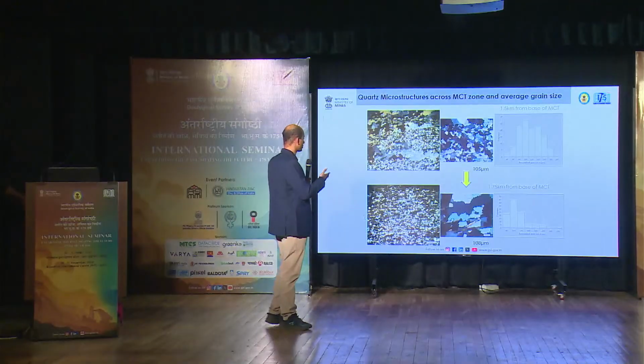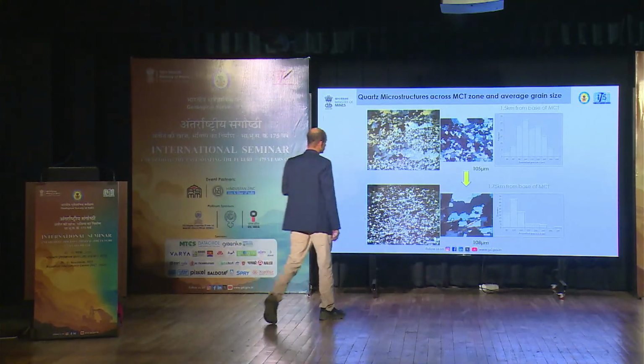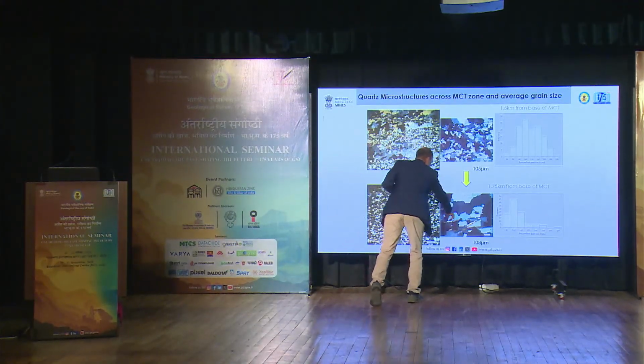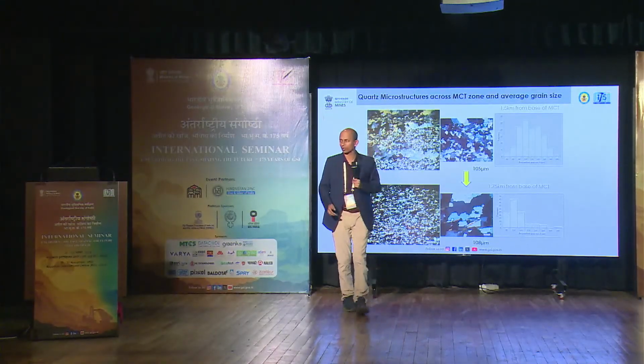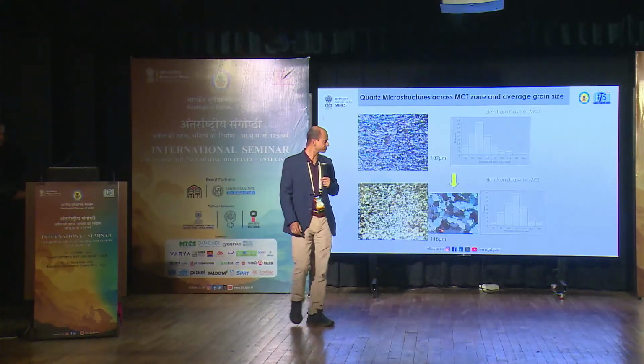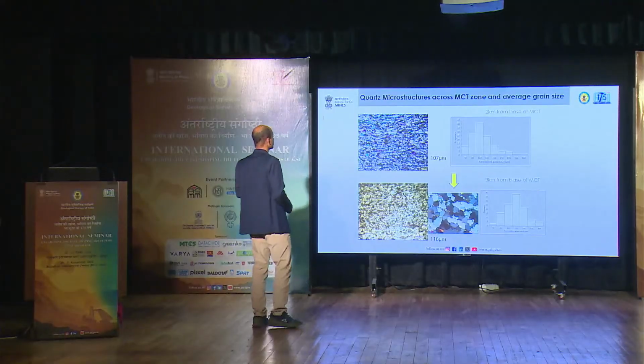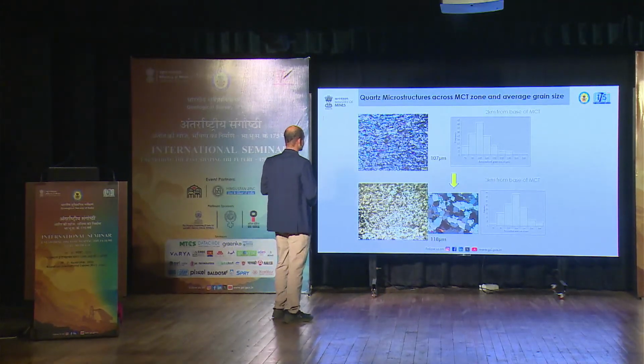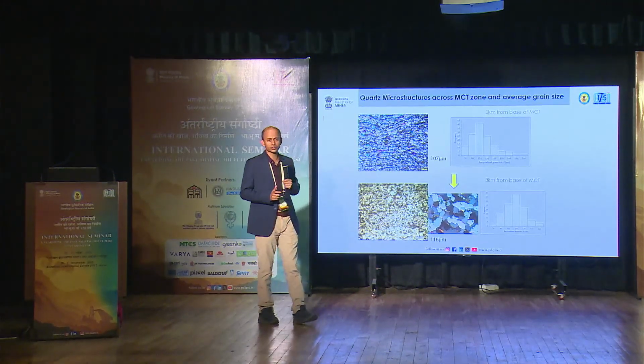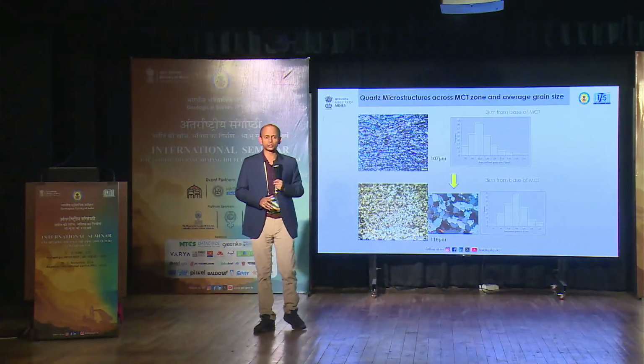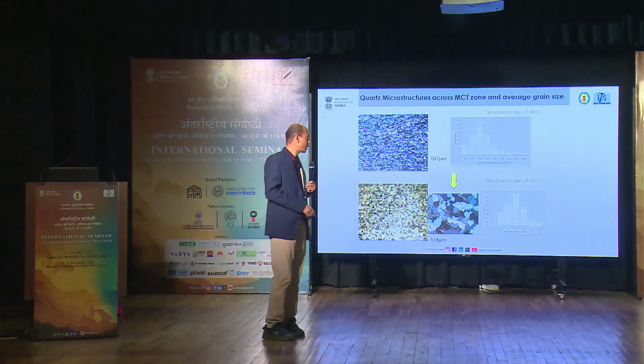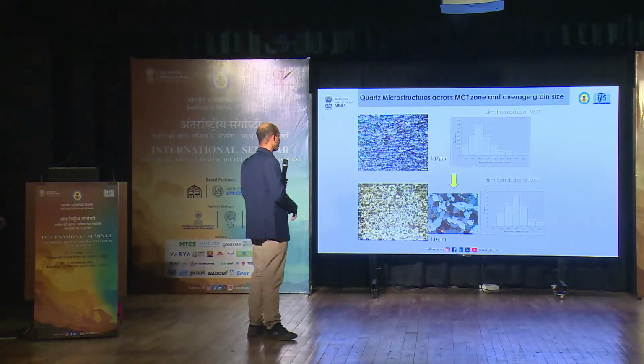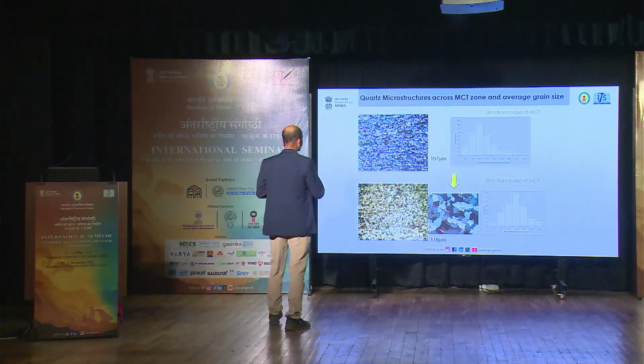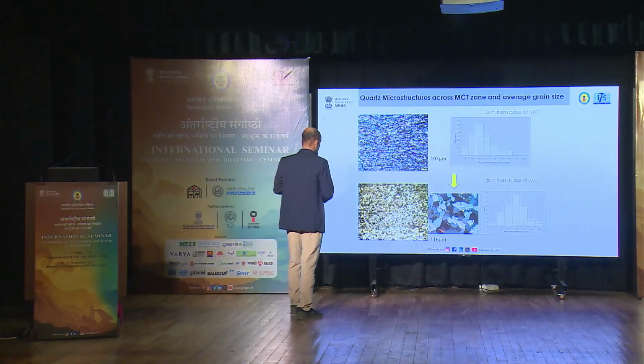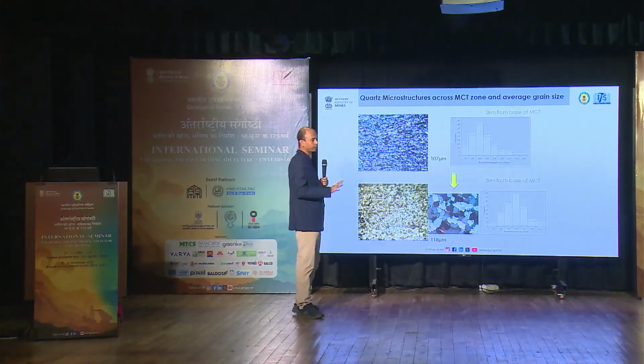We see evidences of window structures here, so beautiful window structures in quartz, evidences of grain boundary migration. Next. At 2 kilometer distance, the average grain size is 107, and again at 3 kilometer distance from MCT zone, base of the MCT zone, near the contact with the higher high-grade metamorphics of higher Himalayan crystalline, we see there is again another jump at 118 micron. We see wide-scale development of grain boundary migration.